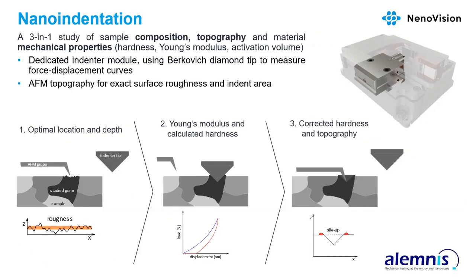Another technique for measuring the mechanical properties is nanoindentation. It is an additional module on Lite Scope. It enables us a 3-in-1 study of composition, topography, and mechanical properties. We see that we have the Lite Scope in a different configuration, and there is the nanoindentation head. We use a Berkovich diamond tip to measure the force distance curves, and there is an optimal procedure for how to measure.